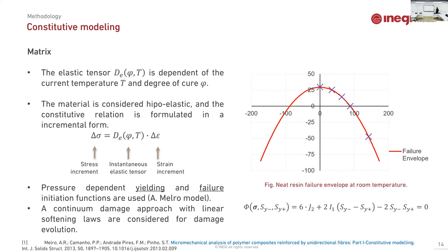Okay. Now we need to simulate the curing process and the behavior of the material to analyze how the residual stresses are developed in the matrix. How can we do that? First, we already know that we have an elastic tensor that depends on the curing degree and the temperature. So we need to formulate a hypoelastic material law to define the constitutive relation. What does this mean? It means that if I have an instantaneous elastic tensor that will change in time because it changes with the curing degree and the temperature, the stress-strain relationship needs to be formulated in an incremental way and not in a total way.